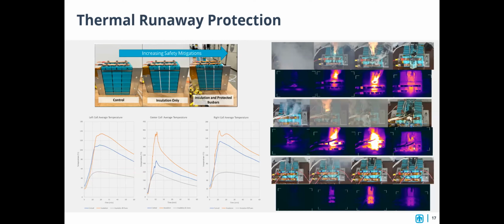And so here is actually an example of heating of cells without a combustion. But if we have both insulation and fuse protection between terminals, what we see is when that center cell is punctured, it will heat, but that heat will not transfer as greatly to the 2 adjacent cells. So it's not just a matter of keeping cells cold, it's also a matter of dealing with the actual electronic connections to make sure you don't initiate a runaway event.